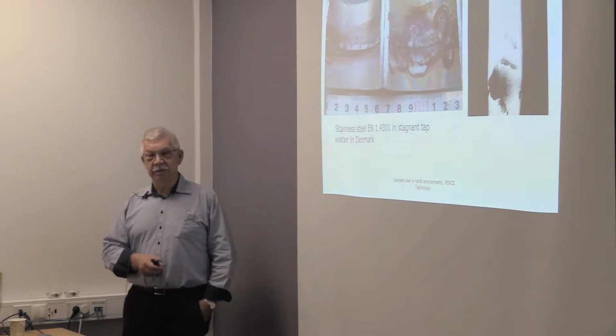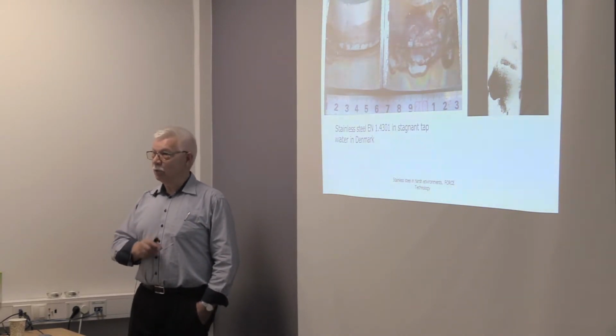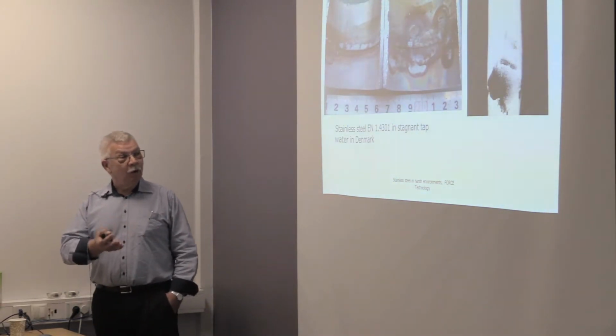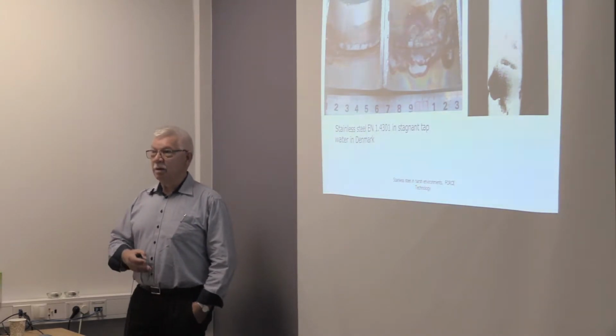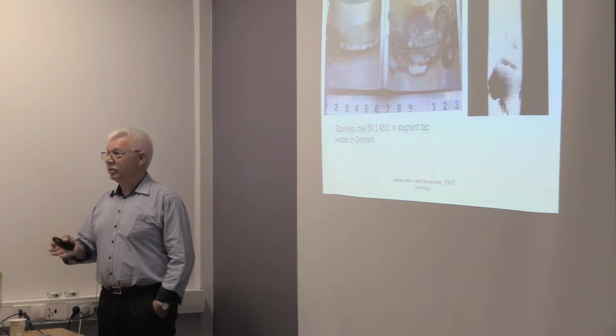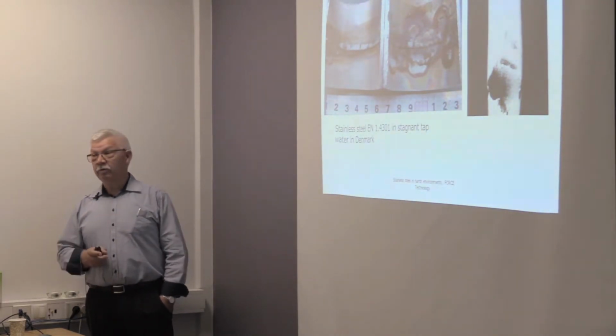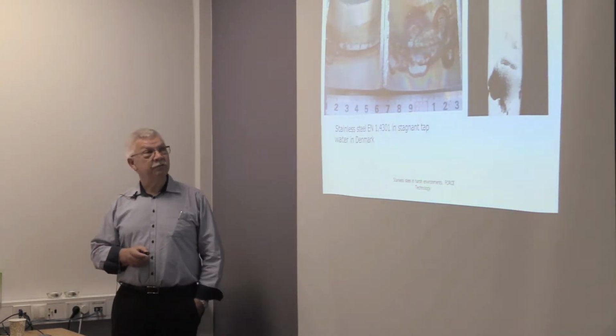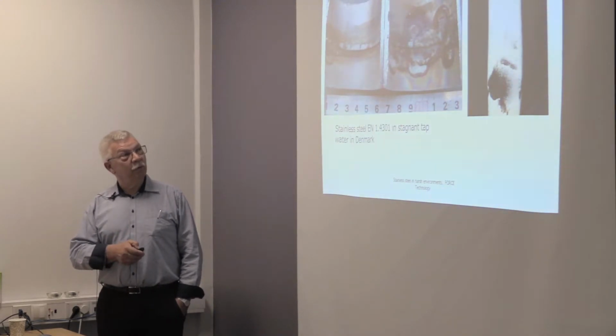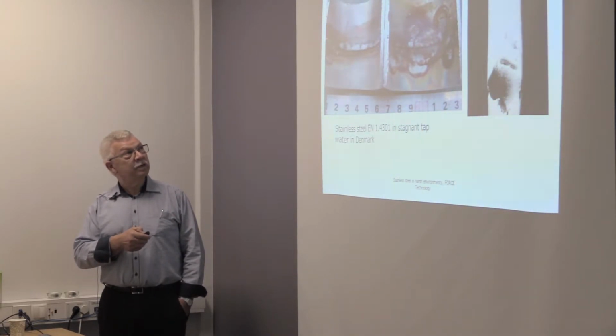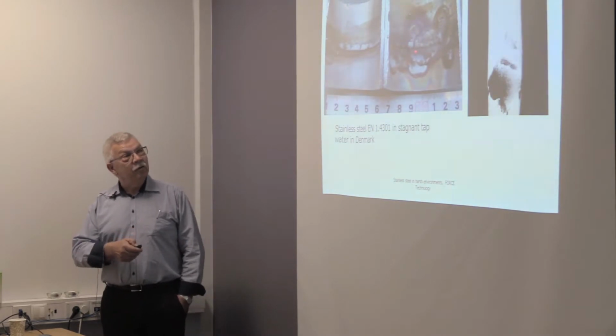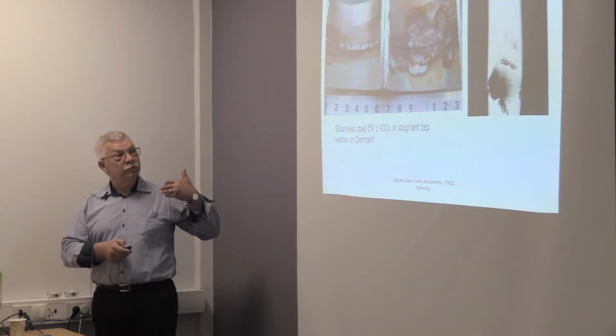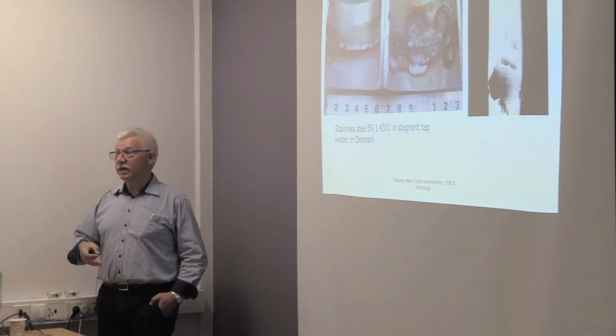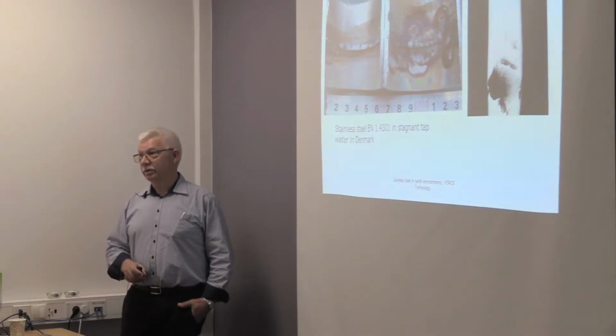So the harsh environment here is stagnant tap water. It's a water supply system where they take ordinary water from the tap, but they don't use that much water at all times. So sometimes it's stagnant. There's no flow for perhaps a week or so, and that's enough to cause this problem. And as we talked about before, welding defects such as lack of penetration here, the heat affected zones. You can see up here that it has definitely been colored after welding, and that is causing problems which might have been overcome if we had a higher alloy stainless steel and a better weld condition.